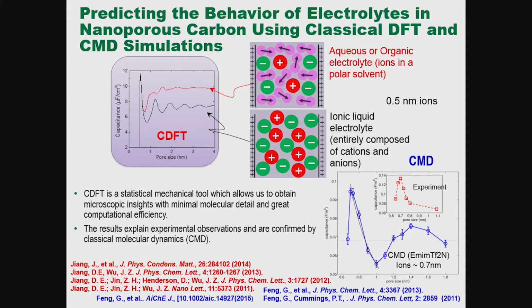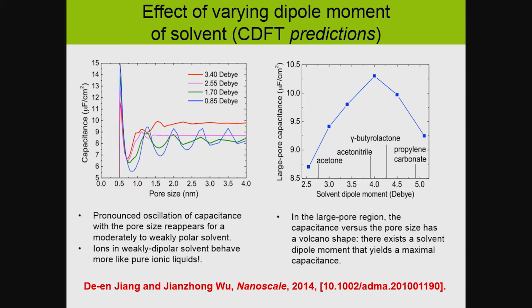We were able to reproduce the first two of these for an ionic liquid, EMIM-Tf2N, in carbide-derived carbon with very careful control of pore size—one pore diameter, two pore diameter. So the first two bumps were reproduced computationally, and the first one has been reproduced experimentally.